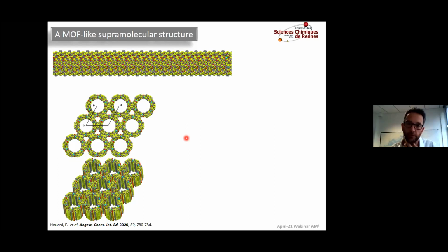Yeah. So we've tried on single crystals on the chains, and it failed immediately. And we even tried on powders. On powders, you can go from chains to hexamers, but not the reverse. When you heat up your hexamers, you just destroy the sample. And is this hexamer a thermodynamic end point, or can you fragment that hexamer into smaller units? Because it seems weird that the thermodynamic product of the reaction would be the hexamer. Yeah, I totally agree.